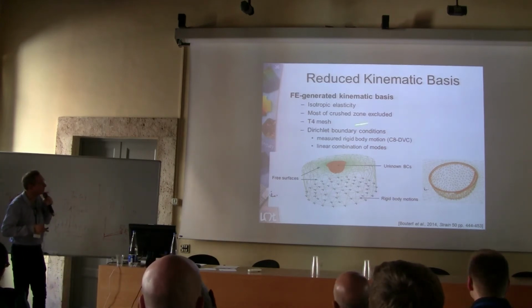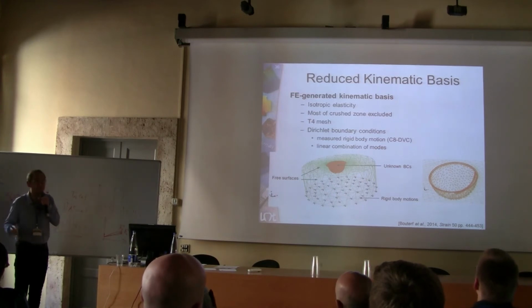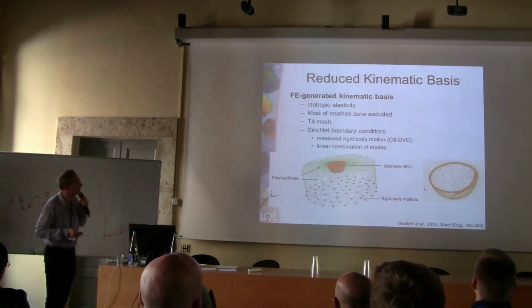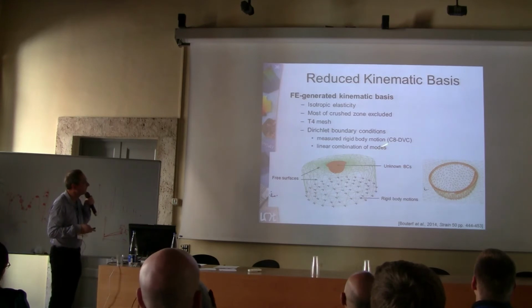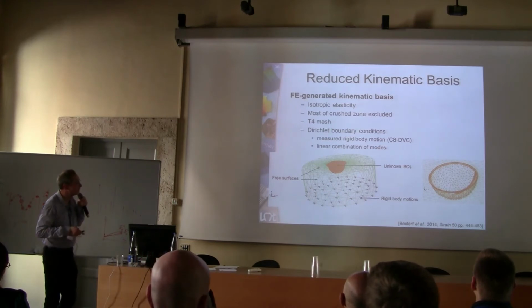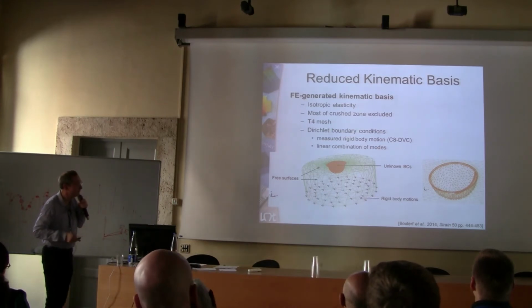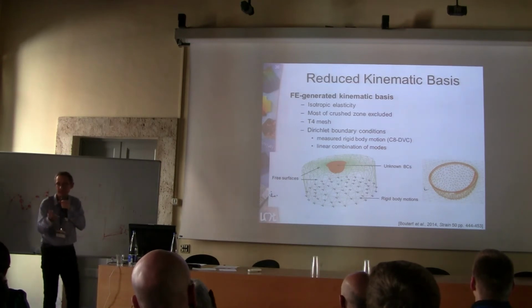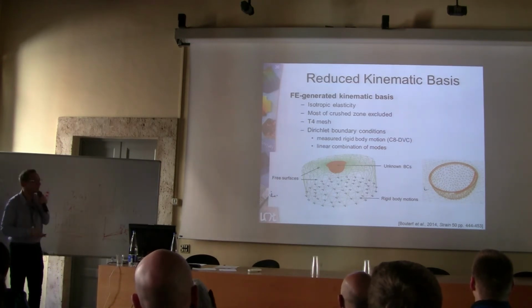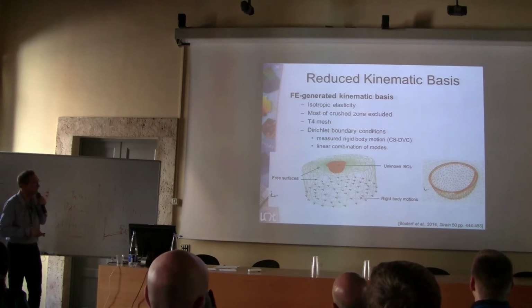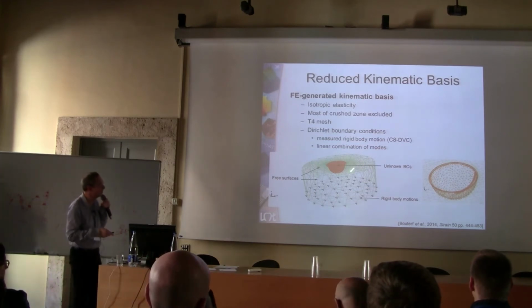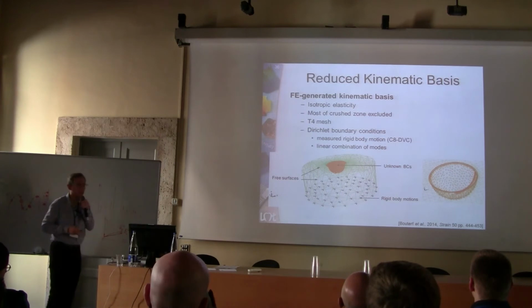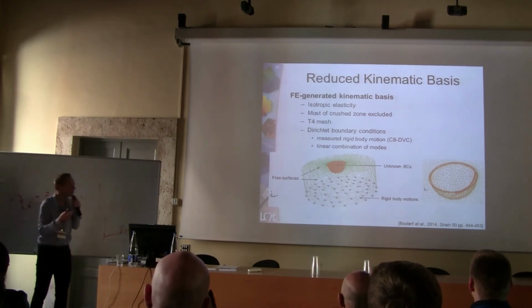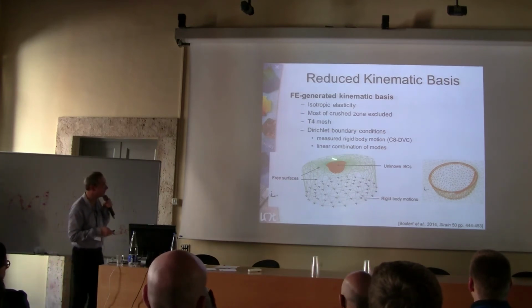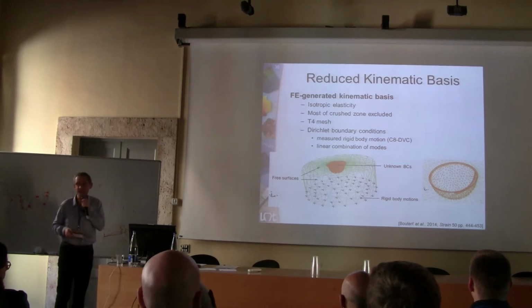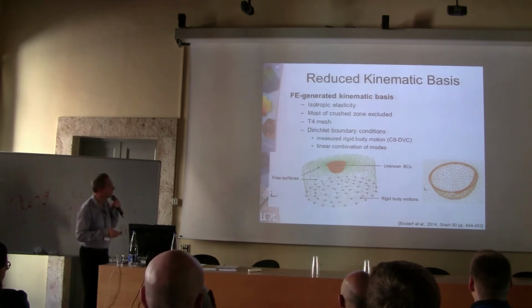Of course, most of the crushed zone has to be excluded because in that part this hypothesis will not be correct. So what we will do is prescribe on the bottom part what was measured with standard DVC, using rigid body motions, and determine the boundary conditions in terms of a few kinematic parameters that allow us to get the best match with the experiment.